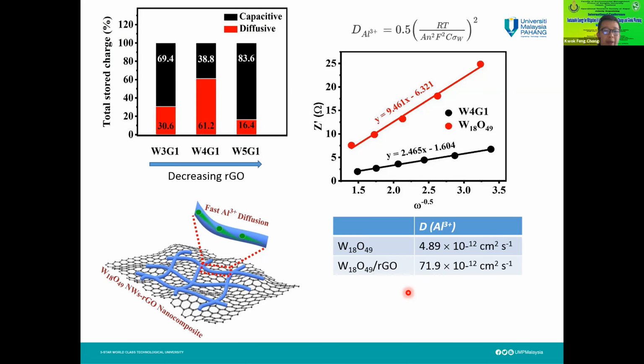But after we put in the graphene, because of the higher conductivity, the diffusion is increased to roughly 17 to 18 times higher. So it proved our hypothesis that when we put in the graphene, we can improve the diffusion of this aluminum ion. So that's why we can have very fast aluminum ion diffusion within the structure. With this very fast aluminum ion diffusion, we can have very high charge storage, because more ions can be stored inside, and be reduced and oxidized within the structure of this tungsten oxide.